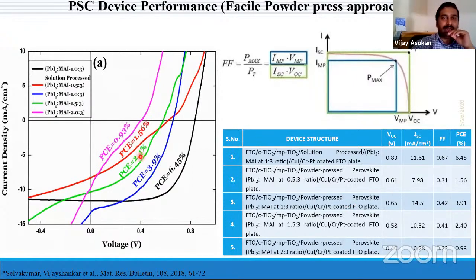We have achieved at least very good in terms of efficiency, at least we can say, within the iodide combinations research. Of course, we reached up to 6.45% at the time, but we try to increase from different scalar parameters. We try to play around those combinations. We finally achieved a few acceptable efficiency limitations.